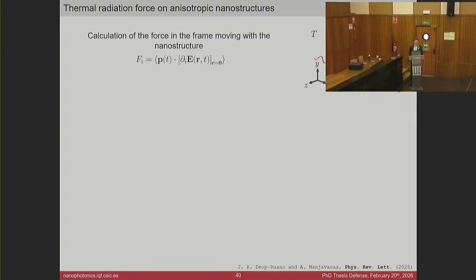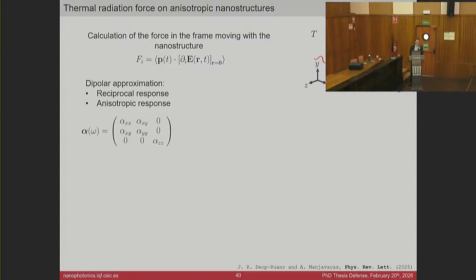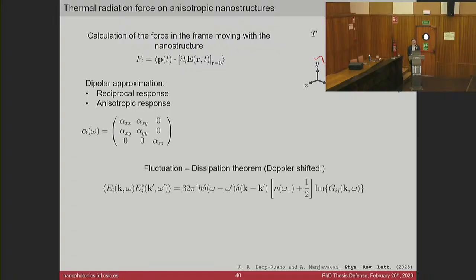Now, I did this calculation by means of a dipole approximation in which the polarizability was modeled by means of a reciprocal response and an anisotropic response, giving rise to this polarizability tensor. We are going to calculate the average over the fluctuations of the electromagnetic field by means of the fluctuation dissipation theorem that relates the average over fluctuations of the electromagnetic field with some dissipation function that, in the case of the electric field, is just proportional to the density of photonic states.